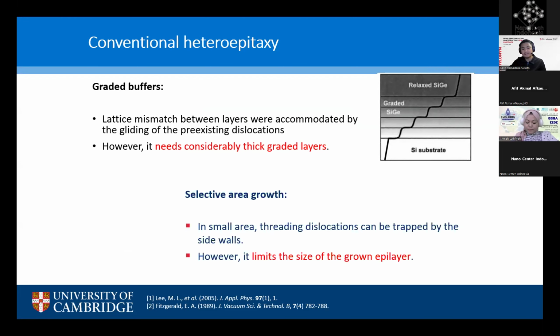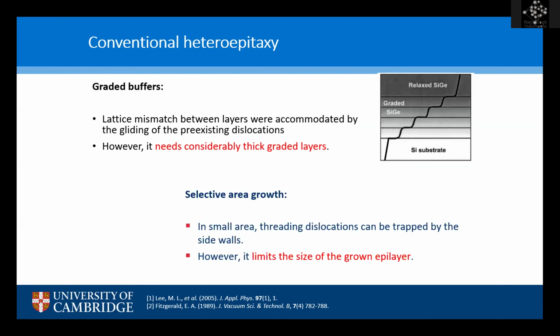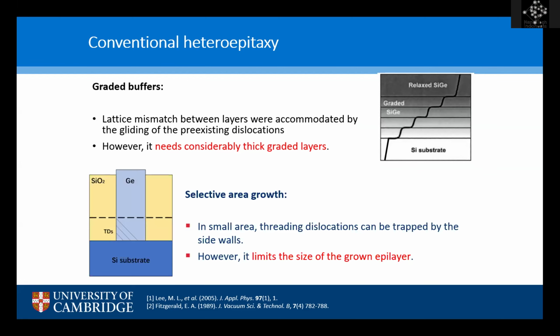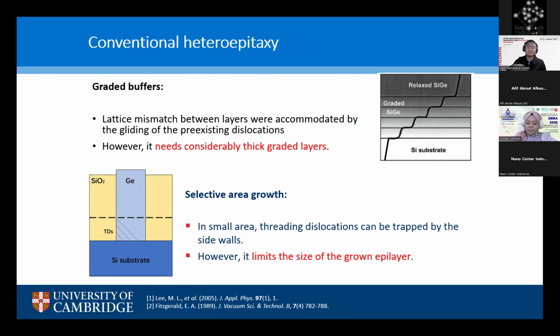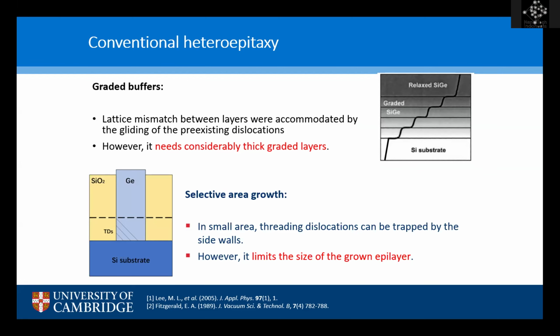And the second technique is selective area growth. It uses the idea that in a small area, threading dislocations can be trapped by the sidewalls. However, these two techniques have limitations. The graded buffers need thick layers, because especially for larger lattice mismatch, you need to have micron thick layers. And for germanium grown on selective area, it limits how large your germanium can be laterally. This limitation hinders the wide industrial use of these heteroepitaxial techniques.